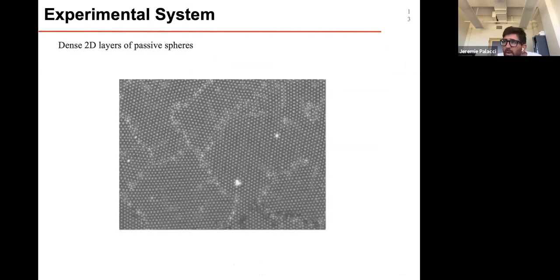So to give you a sense of the experiment, we take the 5 micron spheres, we prepare a suspension of them, and then we let them sediment. They sediment near the substrate, and if the surface fraction is large enough, they start crystallizing. But obviously, crystallites won't all align at once. What you observe is exactly what you see in this picture, about 400 microns across. Those are 5 micron particles. You can see that you form crystallites with a good orientational alignment, separated by grain boundaries, because this crystallite is not aligned with that one or that one. The single crystal is the thermodynamic ground state, and this system will slowly age in such a way that it leads to one large crystal.